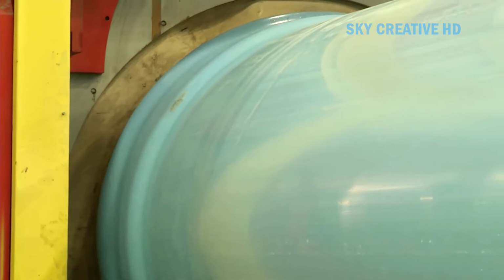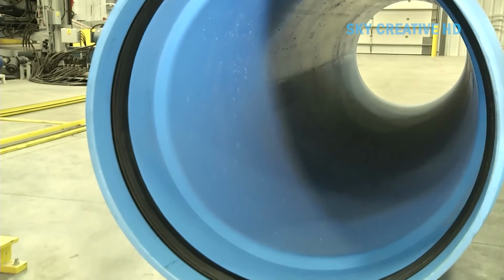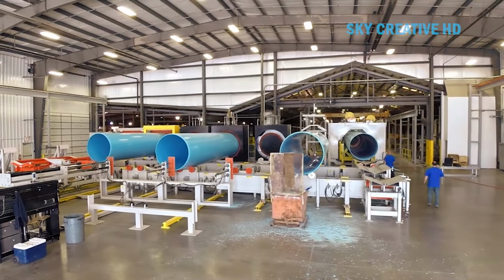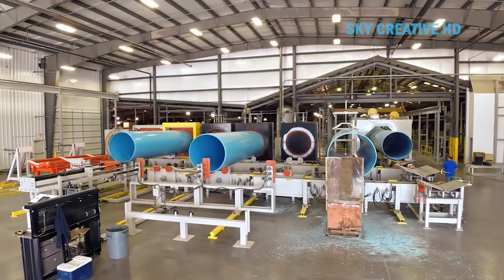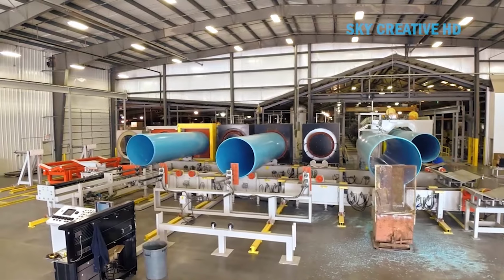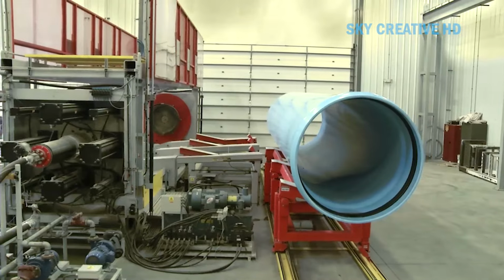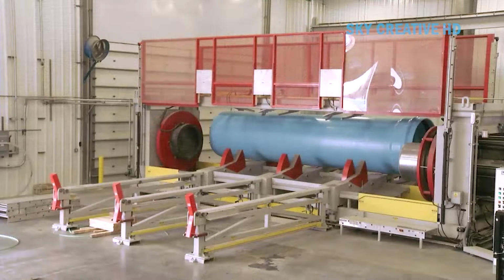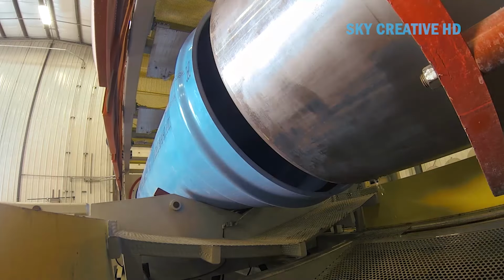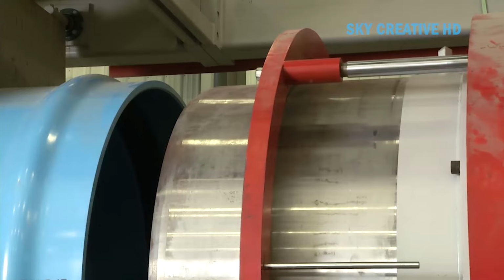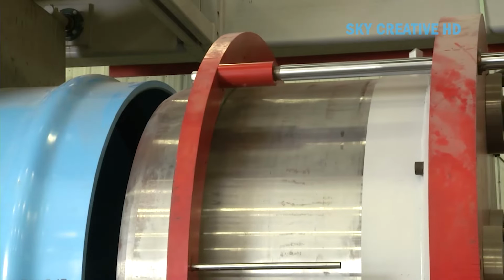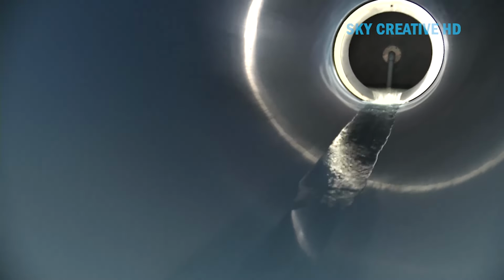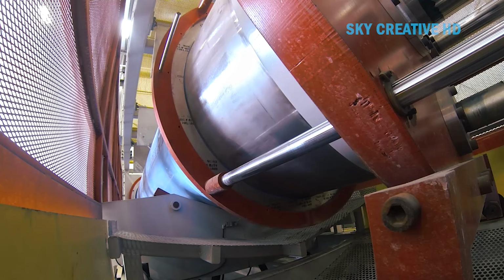And as the pipe emerges, it enters a vacuum sizing tank system. Picture a long water-filled tank, maybe 30 feet long, containing sizing sleeves. Vacuum ports around these sleeves pull the soft plastic tightly against the sizing forms, while cold water cools it. The pipe travels through multiple tanks, each progressively cooling and solidifying the PVC. Cooling rate control is crucial. Too fast, and internal stresses develop. Too slow, and the pipe might deform under its own weight. The pipe then enters the spray cooling section, where mist nozzles provide additional cooling while the pipe gains rigidity.